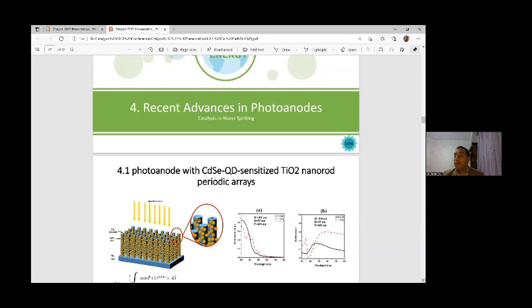This configuration helped us to achieve a scattering mechanism of sunlight and overcome the challenge of the wide bandgap of titanium oxide that I mentioned above. Quantum dots such as cadmium sulfide (CdS), cadmium selenide (CdSe), PbS, PbSe, and indium phosphide have been placed on the structure for sensitization, in which cadmium selenide has better performance according to the literature in comparison with the other quantum dots mentioned above.